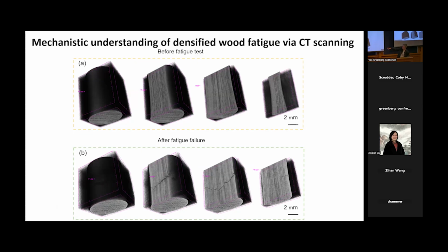This is a snapshot of the scanning, giving you a direct comparison: before the fatigue failure, everything looks perfect. After the fatigue failure, you do see the surface crack start to propagate from the surface, just like the metal samples. It's getting into the cross section, but as you can see, about a quarter of the cross section has not failed. Okay.